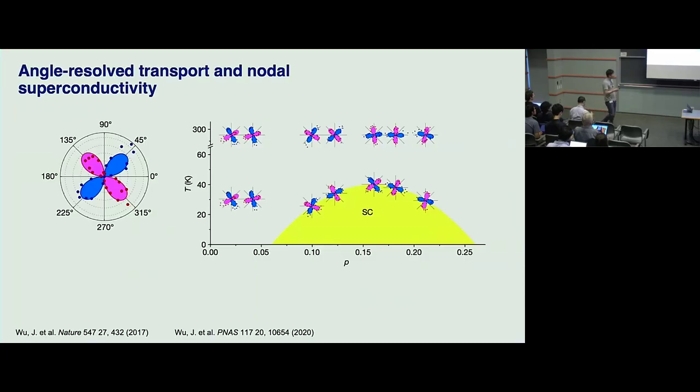But what their observation is, when superconductivity starts to onset, the principal axis, right, the characteristic axis that defines anisotropy, rotates sharply when superconductivity starts to onset. So what they're claiming is that the rotational symmetry breaking must also be intrinsic to the superconducting phase, and they're hinting at some kind of nodal superconducting order parameter, right?